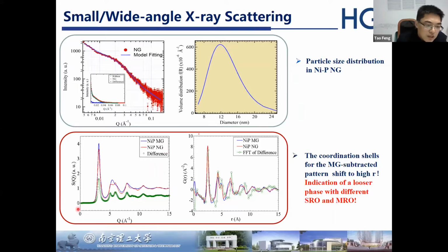If we take the difference in S(Q) between the metallic glass and the nanoglass and transform it to real space, we find the coordination shell is shifted to a higher distance, which indicates there is a looser phase with a different short range order and medium range order in the nanoglass.